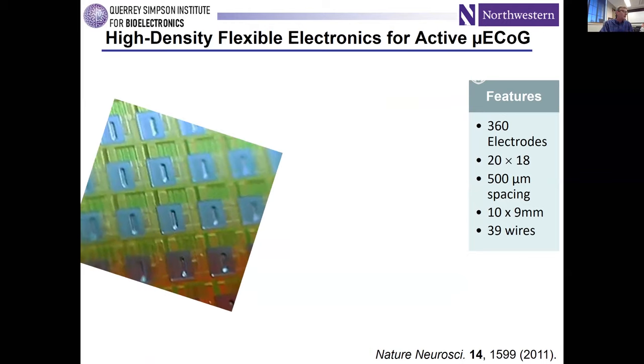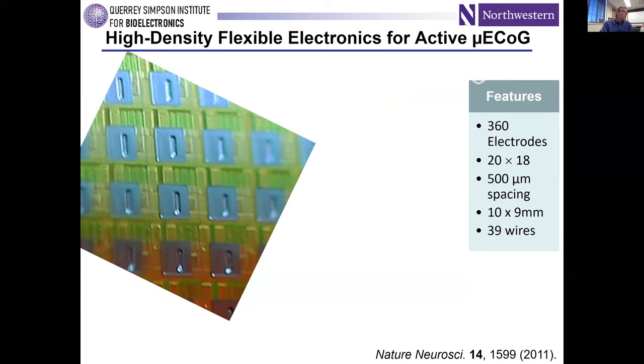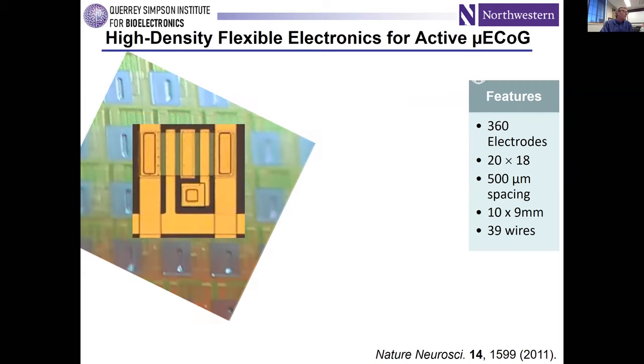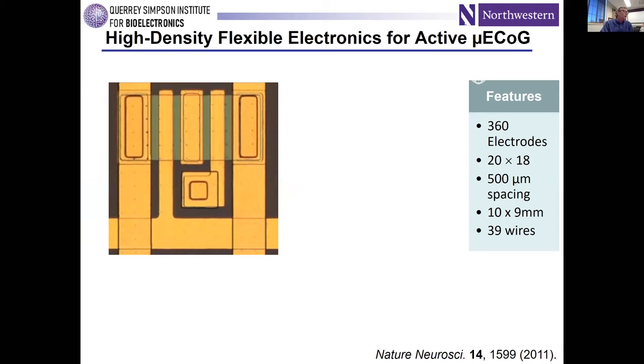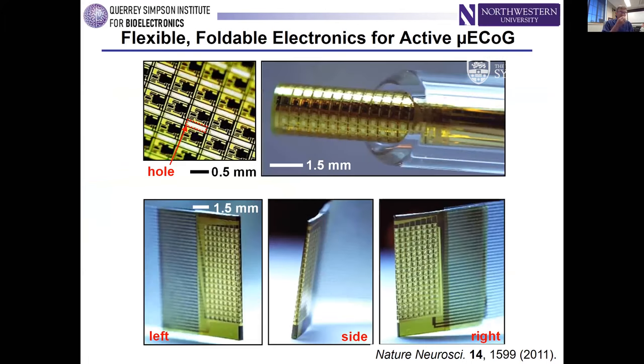And you can kind of see that as I break down the individual unit cell. You see that gray metallization, that's platinum black. It's a low impedance interface to biological tissue, the surface of the brain in this case. And at each unit cell sitting up under those electrodes is a set of electronics. At each unit cell, it's two nanomembrane-based transistors. One is serving as a buffer and amplifier. The other one is serving as a switching element for multiplexed addressing. And so this particular system has a few hundred of such nanomembrane transistors.